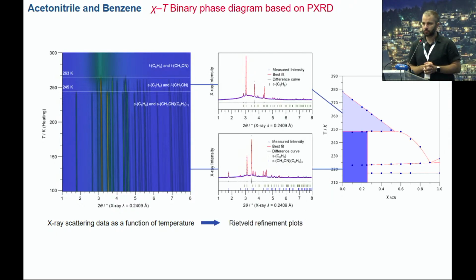What we do in our group, and have done for a long time, is a very detailed analysis of powder diffraction patterns, not just Le Bail or Pawley fitting, but complete Rietveld analysis. For the first region, it's very easy. Rietveld analysis shows that it's pure benzene. So in that region, we have solid benzene and liquid acetonitrile.